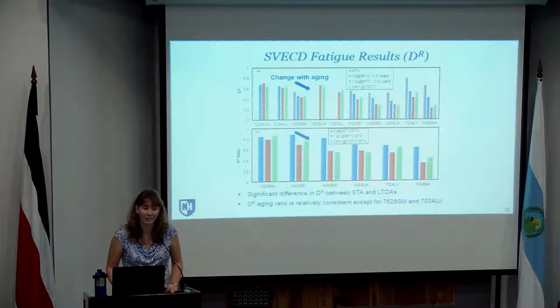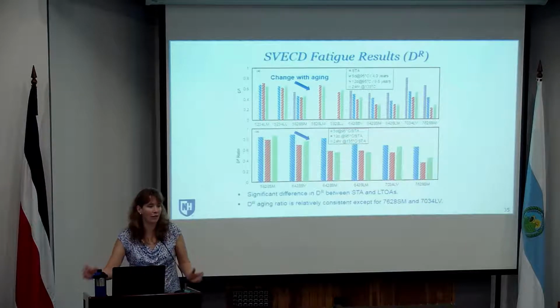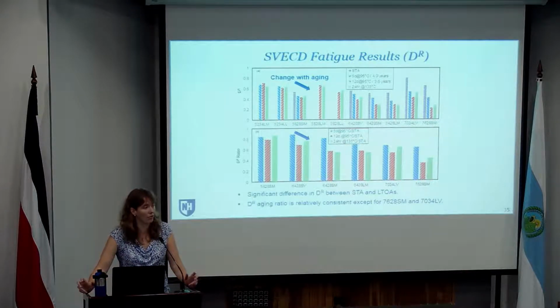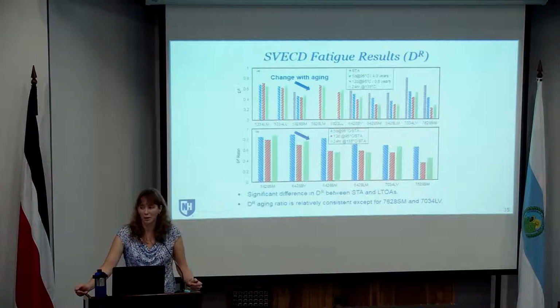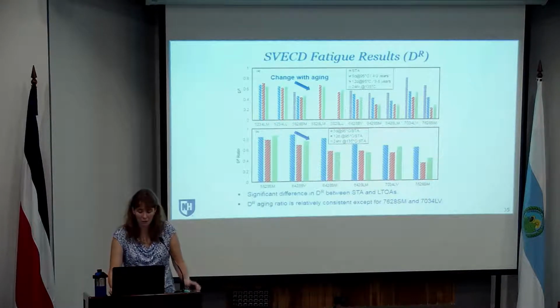And it's not necessarily consistent. It's not always one is greater than the other. Sometimes for some mixtures, they're pretty similar. For some of the mixtures that we've evaluated, one is more severe in terms of the change in the parameter value than the other. And so that's something that's important to realize. Even if an aging protocol shows you the same thing in terms of the viscoelastic response, when you get to the point of looking at what's happening during damage, it can change. It can be different.